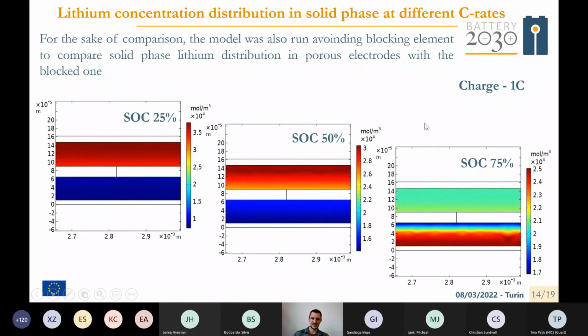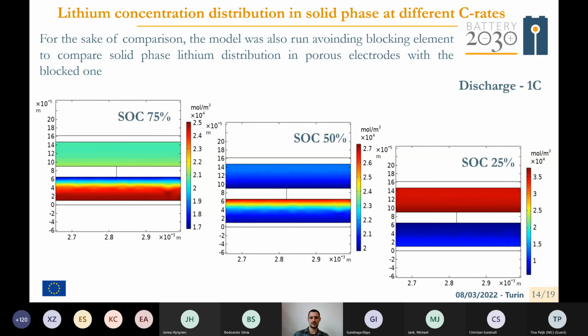So they are basically present, but flattened by the more prominent features induced by the blocking effect. This is the same as in the previous slides, but for the discharge part of the curve, and you can see a complete recovery of the initial condition of lithium concentration of the cell without the blocking elements.